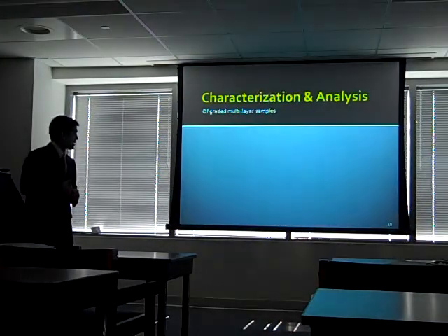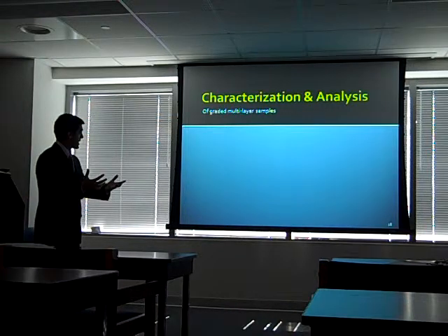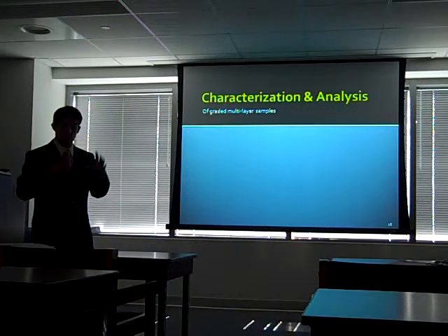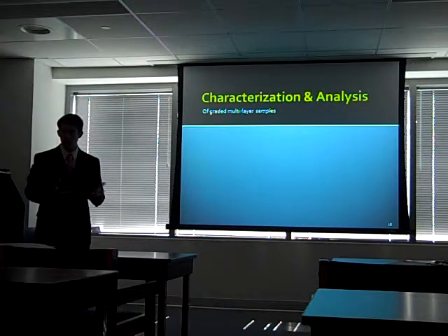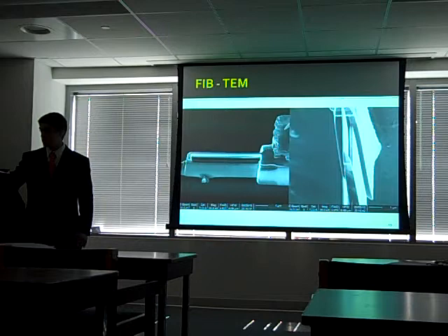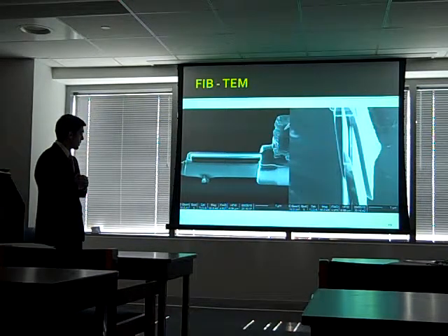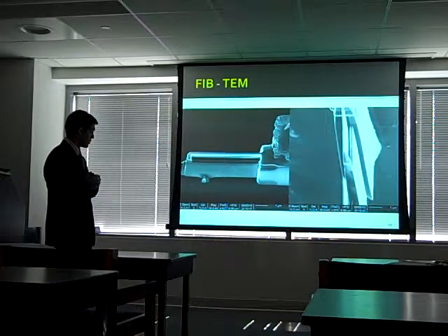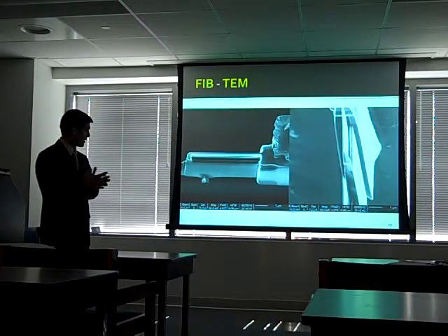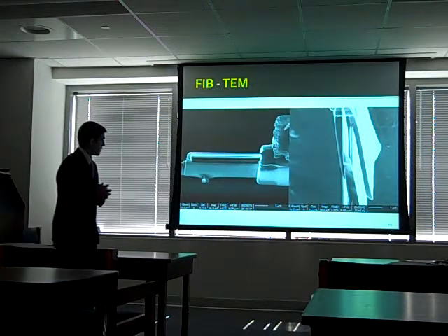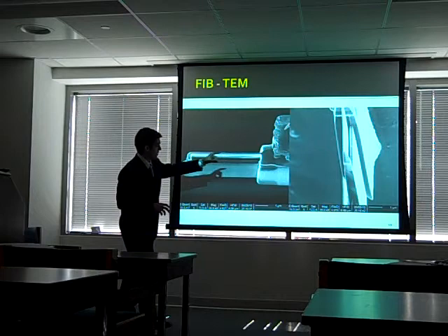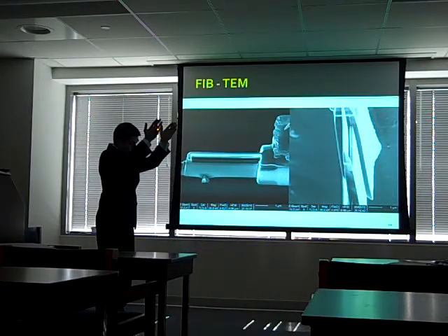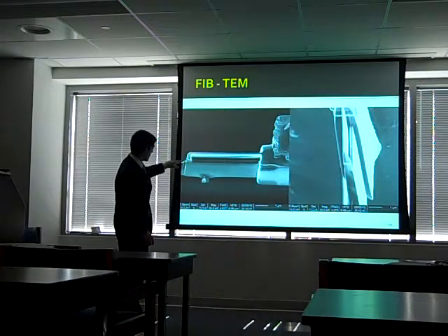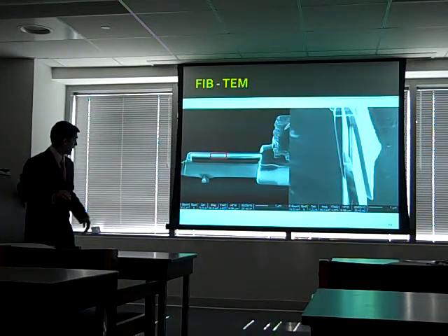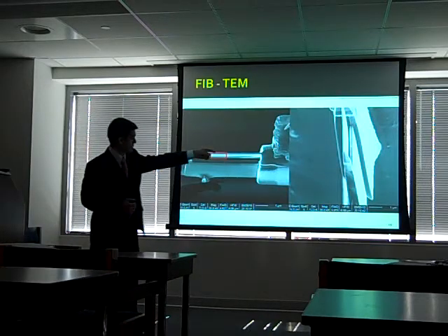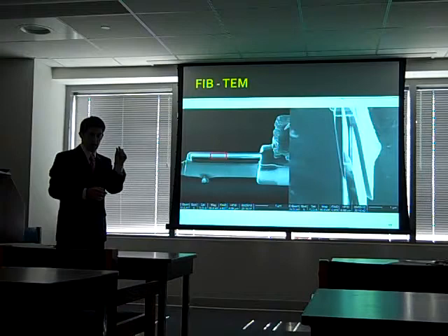Okay, so now the next step in my analysis was to characterize the graded BST structure and to propose a physical model for it. To do this, we used the focused ion beam to prepare a cross-section of the thin films. This is maybe kind of hard to see, but I'll do my best to explain it. This is a front view, and then this is a side view. So basically, if this is the thin film, we've cut into it and pulled out a cross-section. So the BST thin film is right here, and then below is the silicon substrate, and that's a side view. Nominally, the thickness is about 70 nanometers.